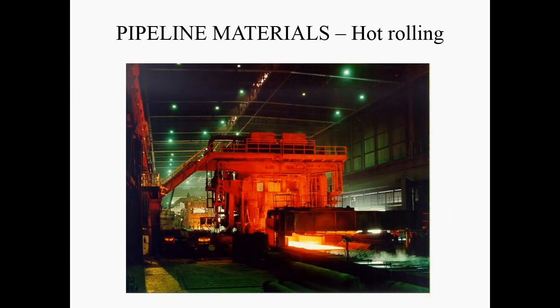Hot rolling mill, huge mill. So there's a horizontal roller here and a horizontal roller here. Well, here and here, in fact. And then you can see the plate coming out. So that previous one was a slab. This is a plate. Slabs are about this thick. Plates are about this thick, or less. And it's big, and it's dirty, and it's messy, and it's heavy engineering.